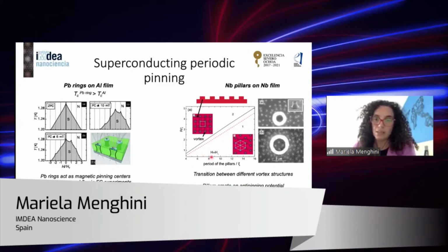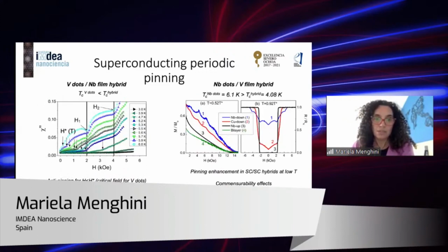And they see here that due to this increase of the length or the thickness of the film in the pillars, this creates an anti-pinning potential for the vortices in this structure. Then later on, closer to now, there are two works that I want to mention, where people have studied arrays of vanadium dots on a niobium film, and the opposite case of niobium dots on a vanadium film.